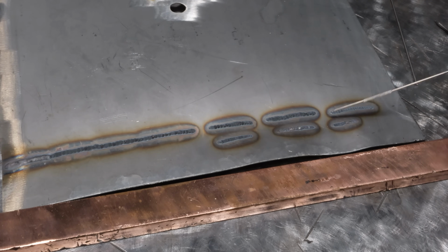Well, yes and no. It really depends on the intended use. This is exactly what the internal welds are going to look like on anything that you don't back purge that's thin, and on thicker material it may end up looking like this, although to a lesser extent. This does not have any corrosion resistance. Therefore, if rust is an issue, or say it was a piping system and all your internal welds look like this, and you put some kind of corrosive material in that pipe, it's going to potentially eat right through this into the weld, weaken the weld, and you could have a failure. So again, it really depends on what you're building.